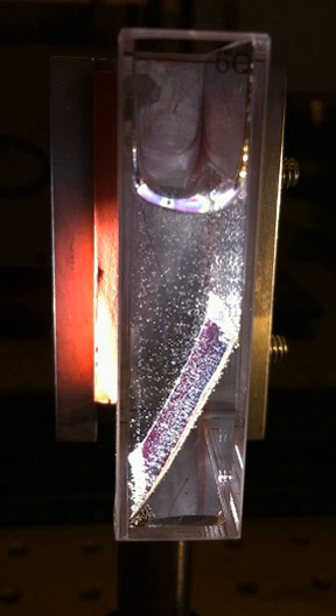Oxides are easier to obtain than molecular catalysts, especially those from relatively abundant transition metals, cobalt and manganese, but suffer from low turnover frequency and slow electron transfer properties, and their mechanism of action is hard to decipher and, therefore, to adjust. Recently, metal organic framework (MOF) based materials have been shown to be a highly promising candidate for water oxidation with first-row transition metals. The stability and tunability of this system is projected to be highly beneficial for future development.